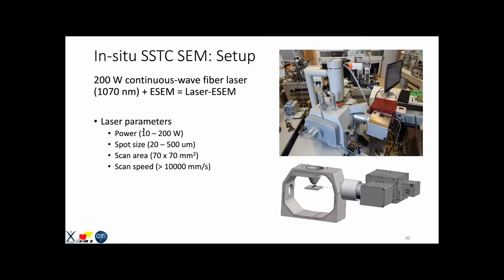So what it can do is that the laser can be tuned from 10 to 200 watts with a spot size varying from 20 microns. So we can do micropillars up to 500 microns. This also means that we can do spot sizes of SLM type all the way to DED type. We have a scan area of 70 by 70 millimeter square, always keeping the same spot size. So that's a large area. And we can have scan speeds of the order of 10000 millimeter per second. So that's pretty large, and we can cover SLM and DED quite well with it.